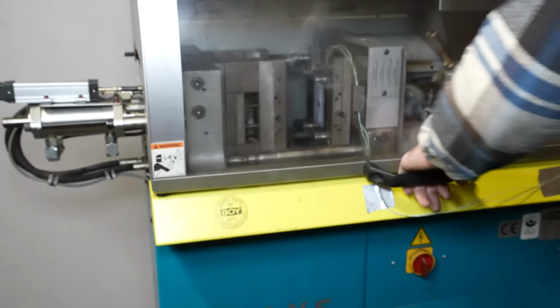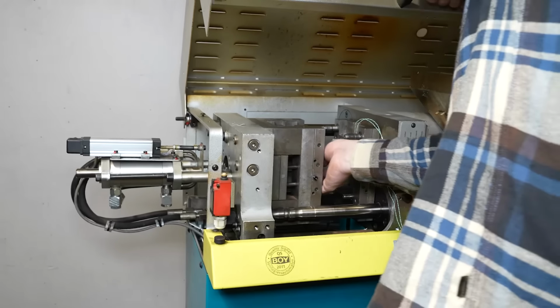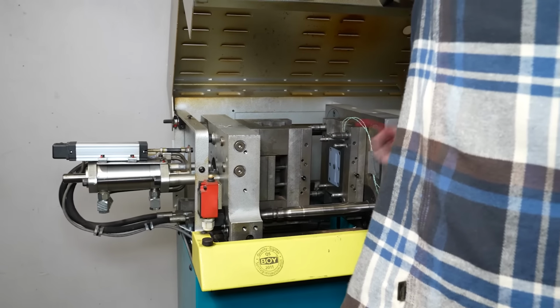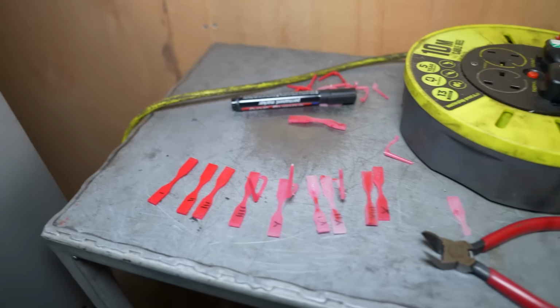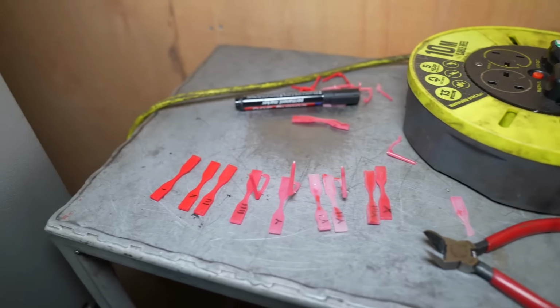We are also looking out for the maximum failure temperature if the mould were to fail in one of these tests. The first material to test was the lower melting point plastic that melts at 160 degrees, which is within the maximum temperature specification for the resin mould material. After around 10 runs of the moulding process, all 10 mould pieces were successful with no damage to the part, which is a great success.